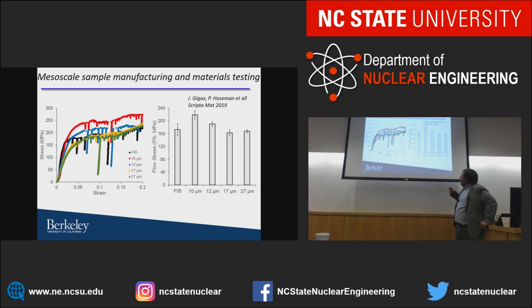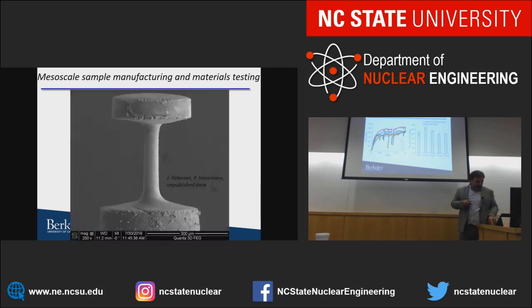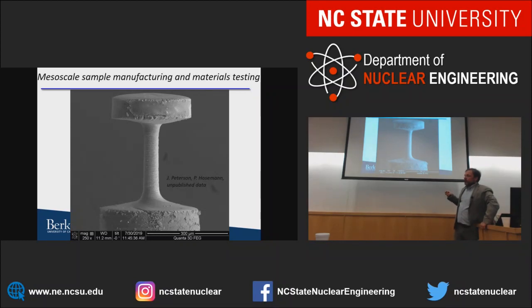So there's clearly damage from that laser cutting. And you have to remove about 3 microns or so from the surface to get rid of all that laser damage. But if you do that, then you get the same mechanical properties as the FIB-cut or otherwise manufactured samples. And very recently, we were able to actually make round dog bones in this mesoscale.